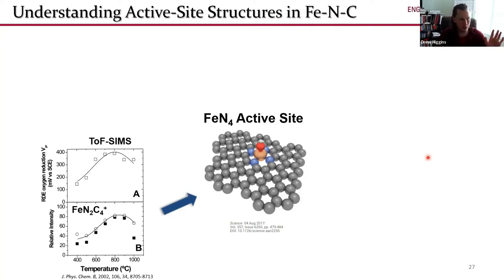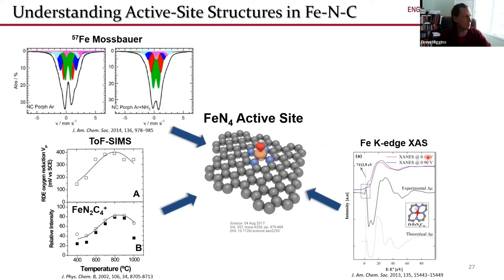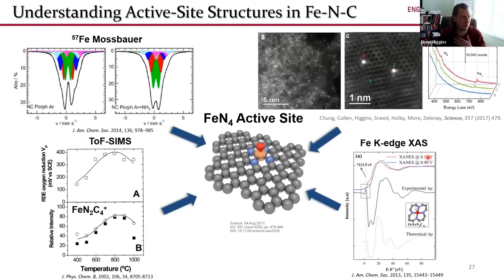And then there was a raging debate for 10, 15 years of, is that actually the active site species present in these materials, or are the active site species just nitrogen dopants that just happen to be near iron, for example? But there's been a lot of follow-up work using techniques such as Mossbauer spectroscopy, X-ray absorption spectroscopy, and even high-resolution scanning transmission electron microscopy that have really painted the picture that, yes, we think it's these iron ions coordinated to nitrogen dopants within a graphitic structure that are the active site structures in these materials.